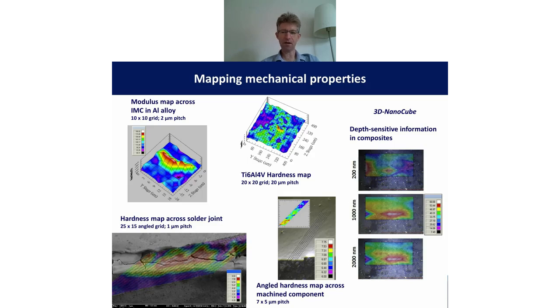and you can even combine mapping with this depth sensitive information, as Andy described it, a load partial load test. And we can do each of those tests in the individual locations, and that allows us to build up slices of information about the mechanical properties going into the material. So in this case, this was in a composite material, and you can see there's a buried stiff phase in there that you're not really seeing at the surface, but as you go deeper and deeper, you're seeing progressively this stiff phase. You're also seeing a pore in this case. So this is very useful for people that are interested in building up mechanical property information.